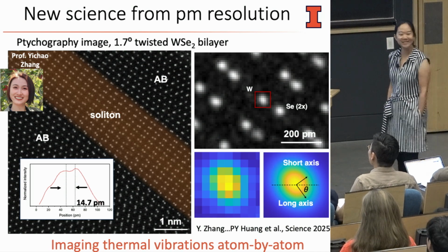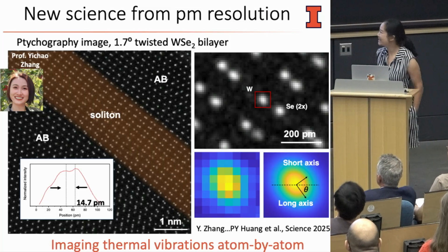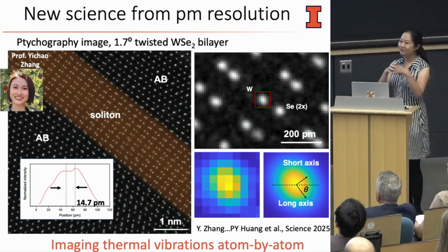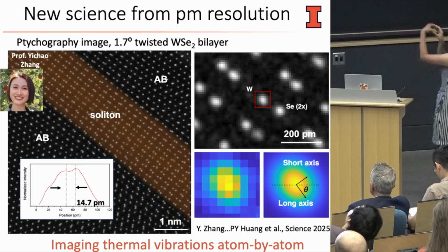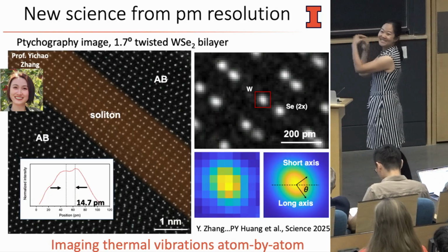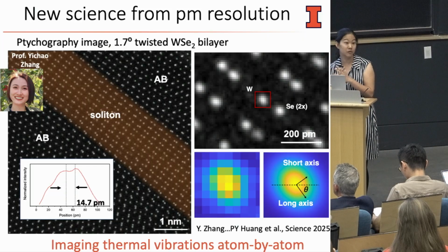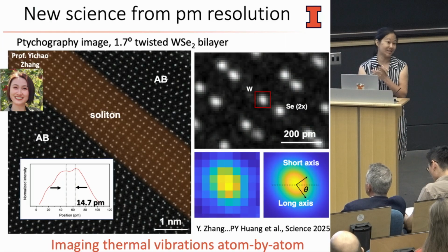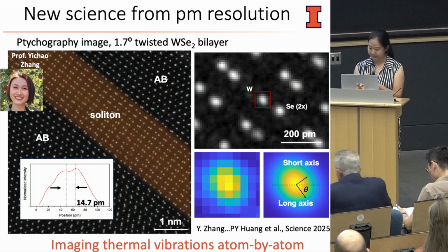No, it's not. Actually, what you're seeing is a type of thermal vibration. The atom, this is at room temperature, vibrates due to heat. It's vibrating not isotropically, but anisotropically, like this. And you can see it with your eye, because we push the spatial resolution so far. So that amplitude of vibration is like 5 picometers, 5.6 picometers in one direction. And that is enough to blur our image correspondingly.